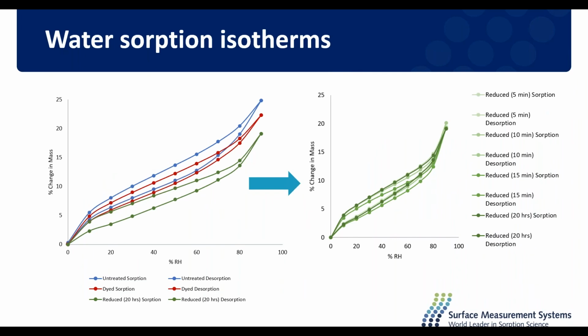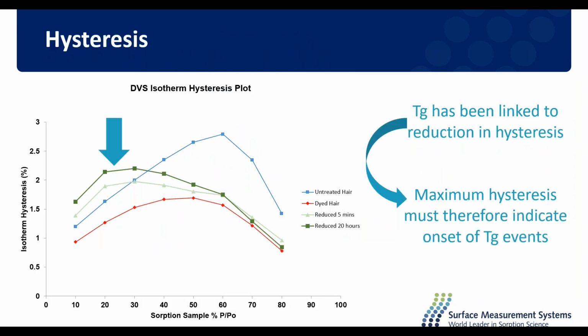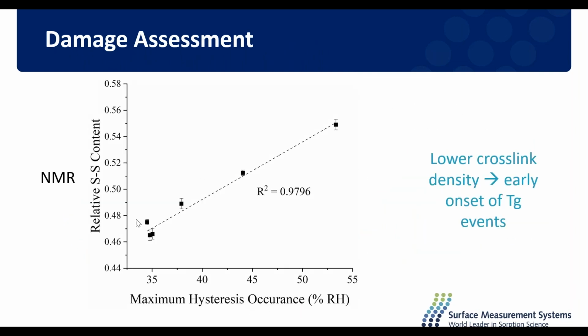As I said in this slide, one of the really big things here was that we introduced some methyl groups, because we had to make sure that those disulfide bonds didn't reform. And so this isn't a perfect experiment. Not many experiments are perfect. And in this case, it appears that the hair samples are very sensitive to any introduced hydrophobicity, with all these reduced samples having very similar uptake. But they do, unfortunately, show differences in their hysteresis, which allows us to have this nice plot.